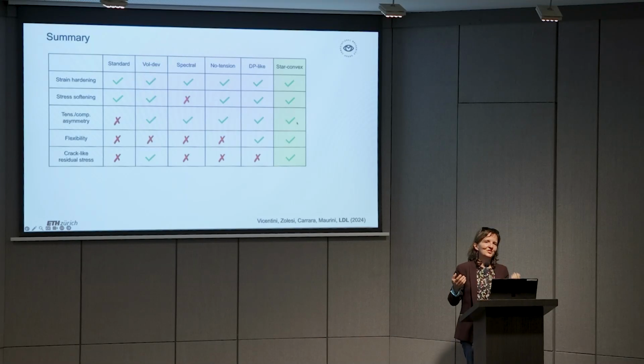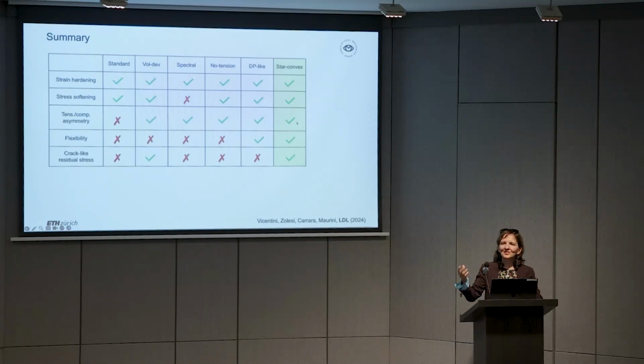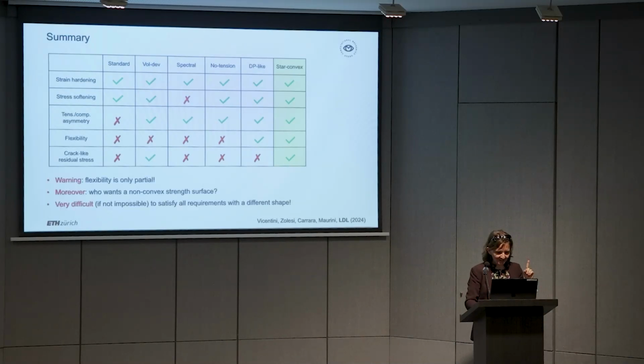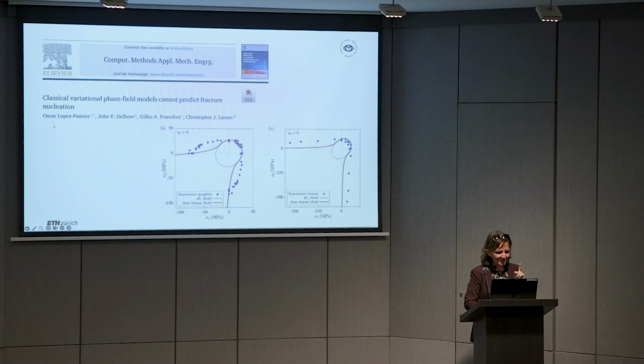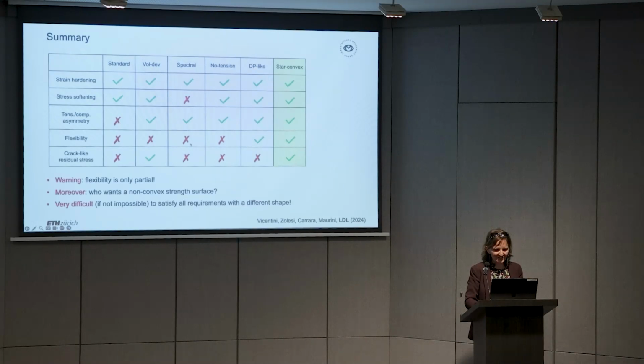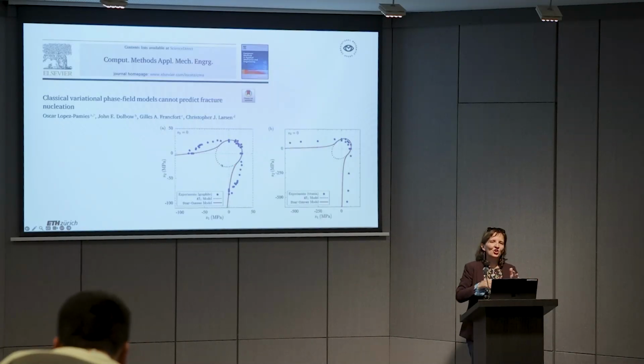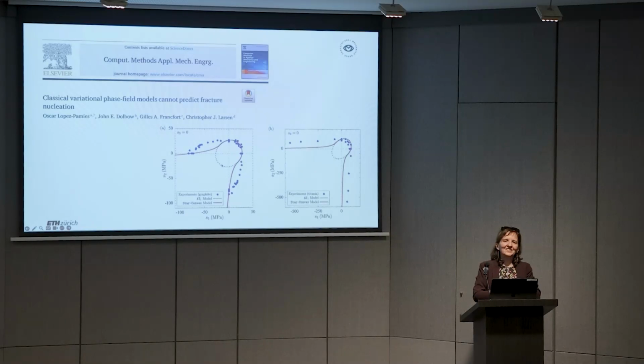Yeah. So it shouldn't be misused though. We have gotten recently some criticism from people who say, okay, the experiments, they don't lie on a star-convex shape. Guess who was this guy? Oscar again. So Oscar published another paper where he takes our model, the star-convex, and compares it to experimental results and says, okay, this model doesn't fit. Clearly doesn't fit. But as I mentioned, the objective of the model was really not to have a realistic strength surface. But still, now we thought we want a realistic strength surface. So now we would like to have really a realistic strength surface.